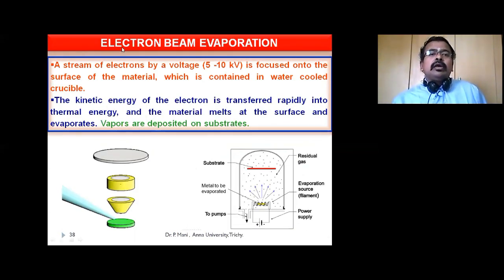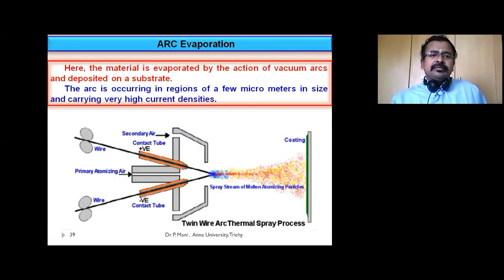First we may see electron beam evaporation. Here, a stream of electrons accelerated by a voltage is focused onto the surface of the material, which is contained in a water-cooled crucible. The kinetic energy of the electrons is transferred rapidly into thermal energy, and the material melts at the surface and evaporates. Then the vapors are deposited on substrates. Arc evaporation: here the material is evaporated by the action of vacuum arcs and deposited on a substrate. Arcs occur in regions a few micrometers in size and carry very high current densities.